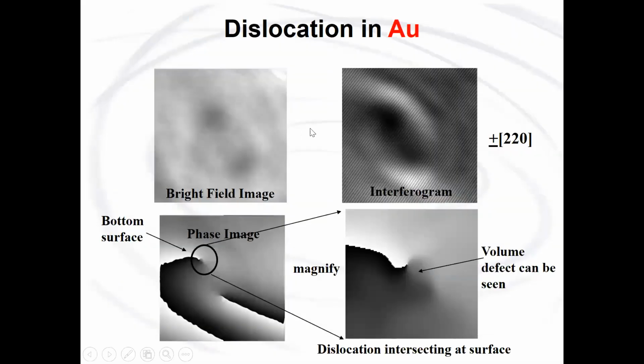The dislocation I'm going to be talking about in this presentation initially looks like this, where we just see two little blobs in the bright field image. When we set it up for exact Bragg, having the plus or minus 220 diffraction vector, we interfere those, and you can see the fringes from the interferogram. When we Fourier transform this to get the phase, we can see the dislocation passing through the crystal here. There are two termination points. This one here is the top of the crystal. This one here is at the bottom of the crystal. If we magnify this region here, we see that the dislocation, as it approaches the surface, goes unstable and forms something that appears like a volume defect.